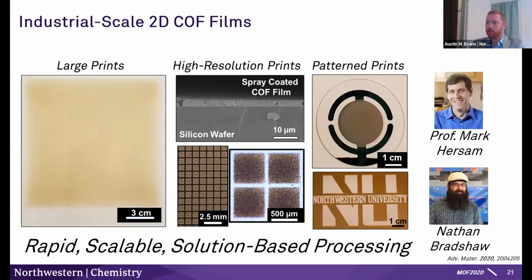So as I already told you, we can create prints of virtually any size. So this large print is, you know, sizable, definitely larger than my hands. The high resolution prints have tight line thicknesses on the order of a few microns, and we can print arrays of those really rapidly. And beyond, you know, just arrays of squares, we can also print, you know, nice circles on a device, which I'm going to talk about more in a minute. And we can also print, you know, patterned words and other things like that, all using a shadow mask. And I'll tell you that all of these prints were done in under 5 minutes.